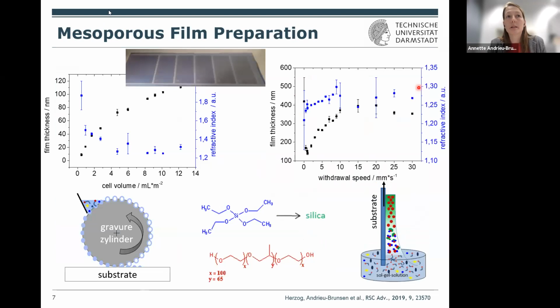This depends. This is all determined basically by the sol-gel chemistry in this process. So basically, the pore size distribution is quite homogeneous because you have this assembly process. So there's not a lot of hierarchy in the system if you take care of that. You might have some micropores depending on the preparation. But this is the advantage of the system. If you think about real membranes, you have a very hierarchical system. And if you take these kinds of model systems, you have a very narrow pore size distribution. And you can do analytics such as infrared spectroscopy, but nevertheless deduce information on the nanopore level, because basically you assume all your pores are similar, plus minus half a nanometer or something.